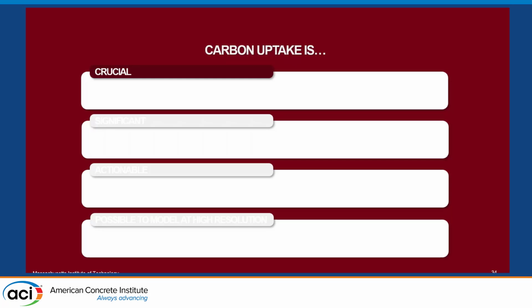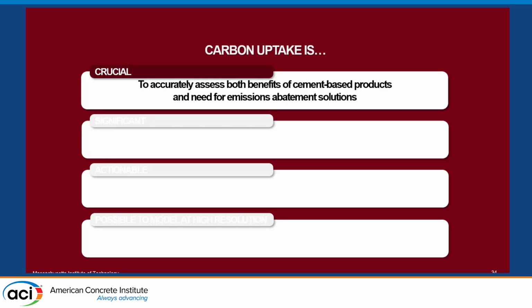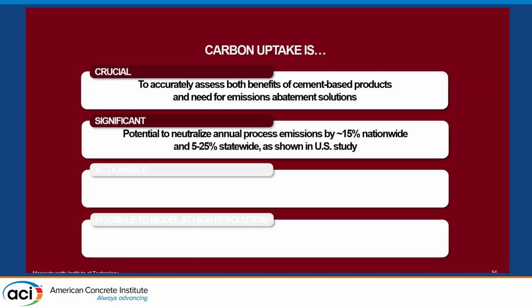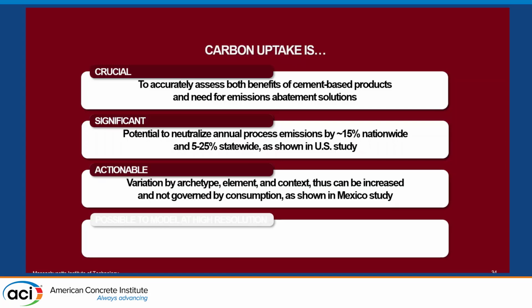So key takeaways. Carbon uptake is crucial to accurately assess both the benefits of cement-based products and the need for emissions abatement solutions. It's significant and has the potential to neutralize annual process emissions by around 15% nationally and 5 to 25% on a state scale, as shown in the US study. It's actionable because we see this variation between archetypes and elements and contexts. Thus, it could be increased by channeling the cement usage to these specific archetypes or elements or contexts. And it's not just governed by the amount of cement consumption, as shown in the Mexico study.